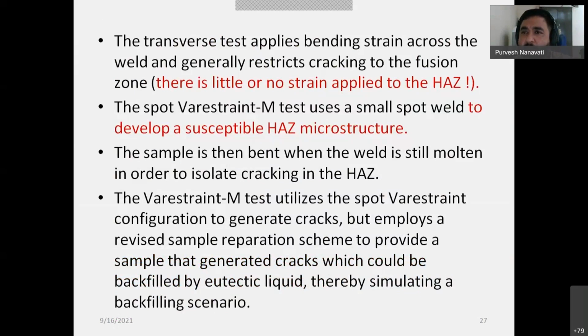The test transfers stress applied to bending stress across the weld and restricts the crack to the fusion zone, right? So there is little or no strain applied to the heat affected zone. You would see that it is in the transverse direction, so most of the stress will be concentrated on the fusion zone and less on the heat affected zone. So there was a further modification, and the modification is the spot Varestraint M test. M stands for the modification.